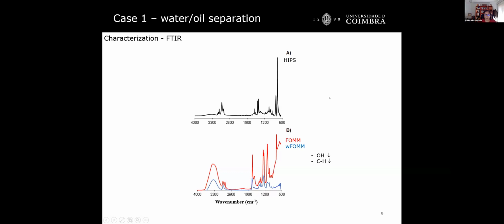Nevertheless, you need to characterize everything that you buy. Why? Because you really don't know if they are selling to you what you're really buying. So for HIPS, we made a characterization by FTIR, and we saw that it corresponded to a high impact polystyrene filament, and then we made it with foam, raw and wet foam, so after PVA removal. In fact, you see, and it's not just because all the peaks have less intensity, you have a decrease in the OH peak and the CH peak, which correspond to the PVA.